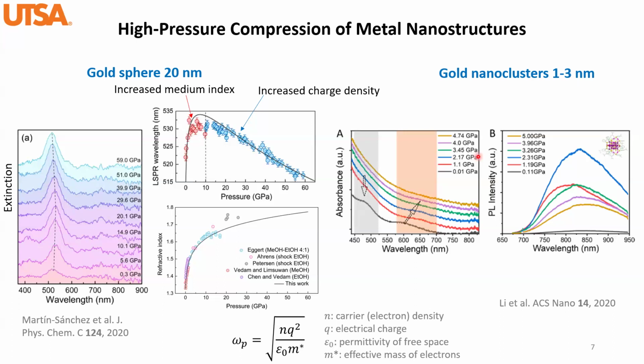Well, but that is probably the point of why we do the research, right? Trying to see if it is possible to apply extreme conditions so that we can change this to have a longer propagation distance. Yeah, my criticism is that you're sort of hoping for a miracle. It's like, oh, maybe I'll find the right system accidentally that'll do this, rather than coming at it from both ends. Because what should it really look like to minimize or eliminate the plasmon-phonon scattering? That would be a really big deal, not just for transport, but for catalysis. For everything, right? Right, because you get much more hot electron transport.